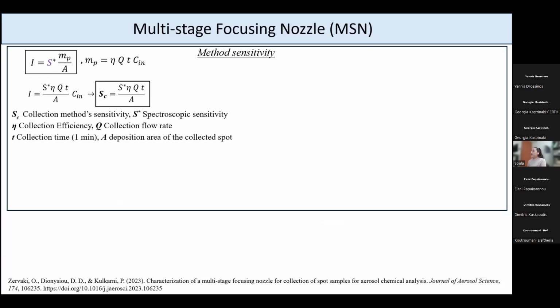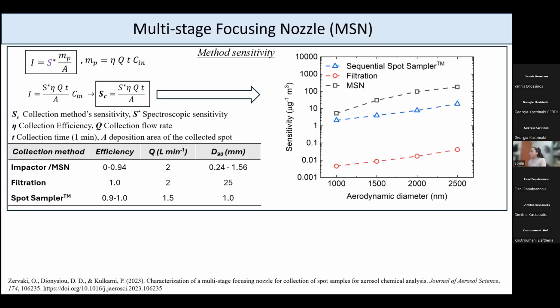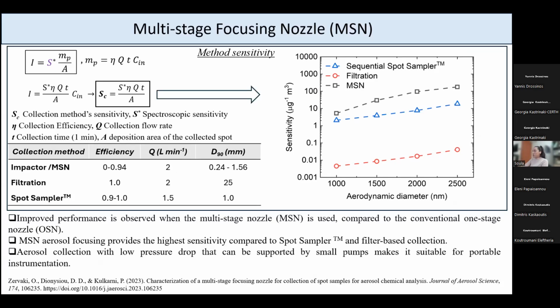In this way, depending on the collection method that we use, we can calculate the sensitivity of the measurement, and we can do a theoretical comparison. And this is what I did here. We see that when the multi-stage nozzle is used, we can achieve higher sensitivity compared to other conventional aerosol collection techniques. And that concludes this study, where the multi-stage nozzle shows better performance compared to the conventional one-stage nozzle.